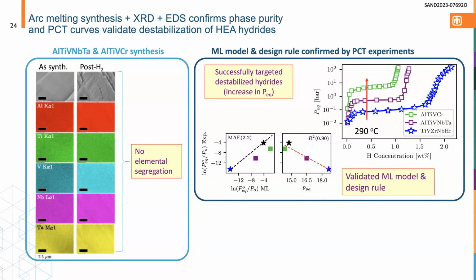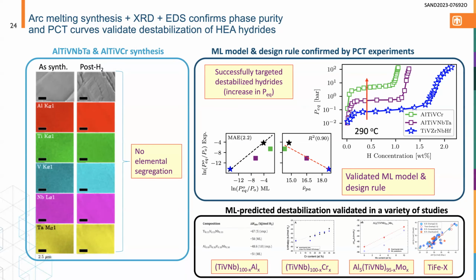If you click again, I'm just showing that essentially the machine learning model did reasonably predict the new equilibrium plateau pressures for these compositionally modified high entropy alloys. And on the right is the equilibrium plateau pressure versus that new PA descriptor, which I mentioned, which has a log linear correlation. So again, it helps also validate the machine learning design rule, the first order machine learning design rule.